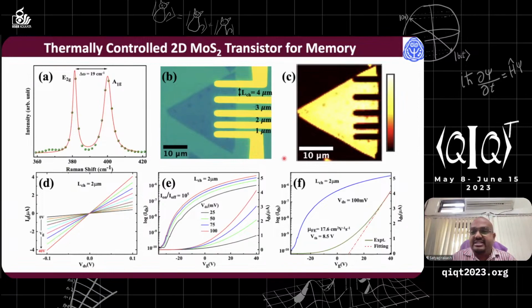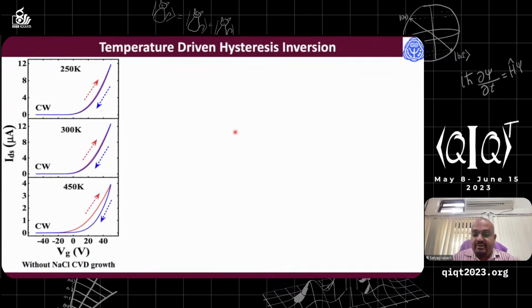So these are the basic characteristics of the MoS2 transistor that we have made, and we are regularly making these transistors in our lab. And what is important is a very striking feature I am going to discuss here. You see, this is the hysteresis characteristics of a monolayer MoS2, which is grown without NaCl involved. Because while we grow the sample, we have two categories of approach, where in one we use some kind of salt, and in the other we do not use salt. The advantage of using salt is that it acts as a catalyst and grows a large area MoS2 when required.